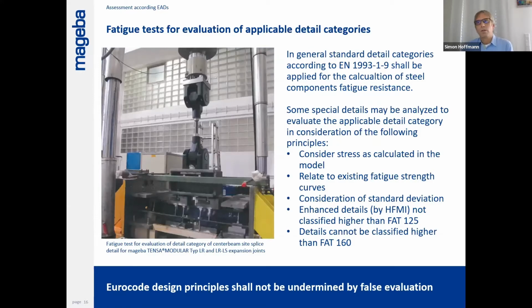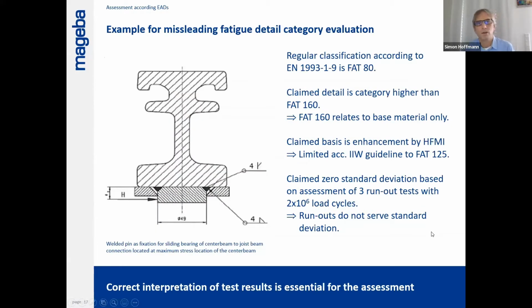Even more important from our point of view is to have really experienced partners in the field of evaluation of applicable detail categories, because we see some undermining by false evaluation. Here is one example where we have a fillet weld of a detail at highest stress concentration within the modular expansion joint, which is classified according to EN 1993-1-9 as fatigue category 80, while it was claimed that this should be higher than fatigue category 160, while 160 is the highest category available in that code.